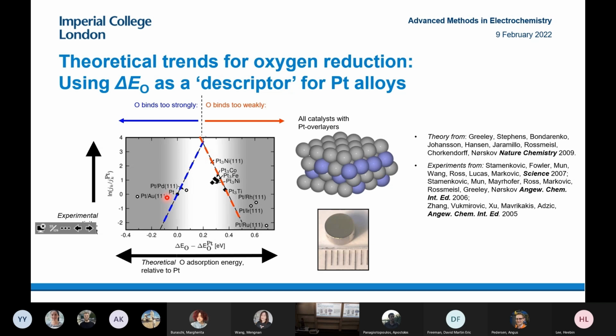I think it's not as convincing as my own data on the platinum copper near surface alloy, because there we had experiments as a function of composition, but it's still interesting anyway. So a lot of these surfaces, like platinum nickel and platinum cobalt, have a problem when they're actually used in fuel cells: they work quite well initially, but they tend to de-alloy with time.